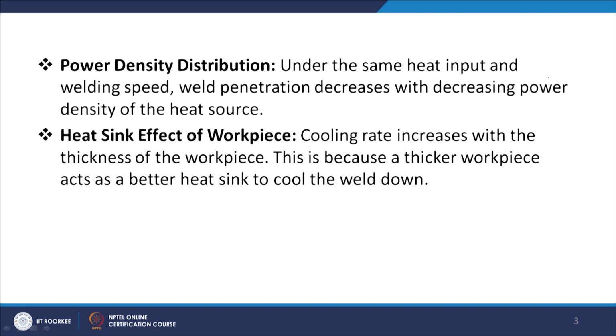Then we talked about the power density distribution. In the case of power density distribution, it will be governed by certain physical parameters, like the electrode tip angle. It has been seen for gas tungsten arc welding that the tip angle can be smaller or blunt. So, in this case it is blunt, and in this case it is made taper.